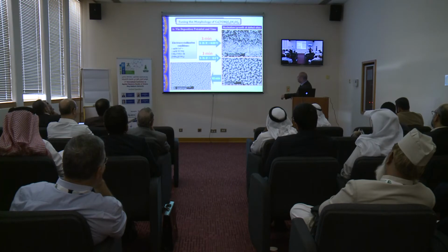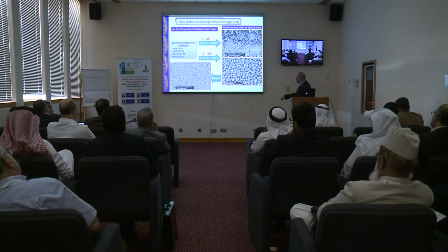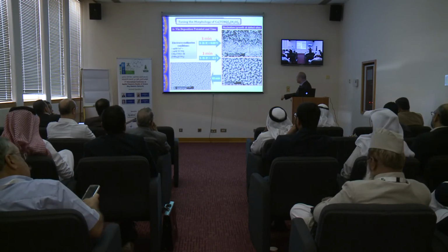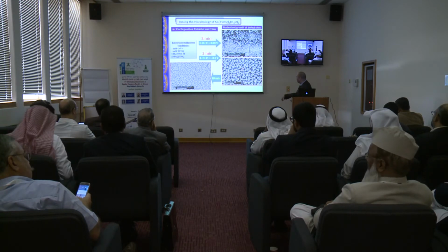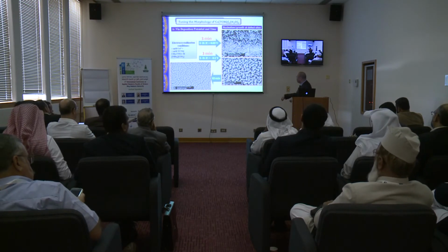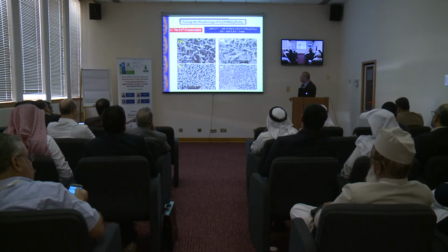However, if you apply a different potential, not this one, the most negative one, which is minus 0.1, then you can get a different morphology than what you can see here. You can see this hexagonal shape are not fully filled with the material, not the building up. So if you leave it for a long time in the electrolysis cell, you can have this crystalline film.